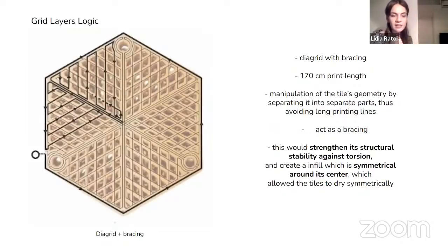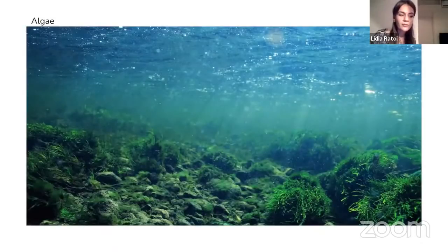And that gave us, first of all, shorter printing lines. And the tiles were symmetrical around the center. So that means that they were drying symmetrically and we didn't have cracking anymore. And the other problem that we had to account for was, as I said, the competing species.